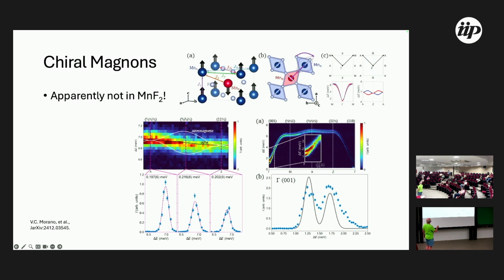And I guess it turns out, and you could imagine that this is the case, right? Because between these two, there are fluorines in between. Between these two, they are not. But I guess there's not a sufficient amount of difference in the anisotropy between these two. My guess is because really the exchange, instead of going from here to there, goes from here to there to here to there to there, right? And so then this one does something very similar. And I think that's probably ultimately why it's not so different.